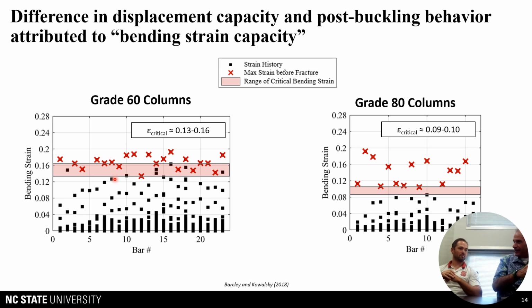And at that point, upon reversal, that bar had fractured in that column. So what we did was to say, okay, let's look at all this data and find out where is the value of the lowest X, the lowest fracture. Well, that was right around 13%. What's the value of the highest unfractured bar? That was about 16%. So what we inferred from that was that the critical bending strain you can sustain for grade 60 steel is somewhere between 13 and 16% before the bar fractures.